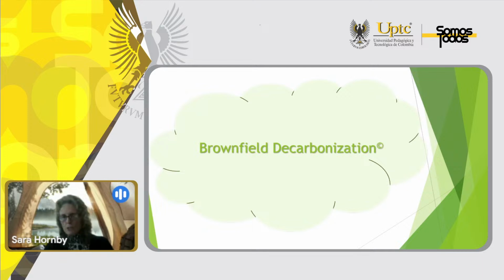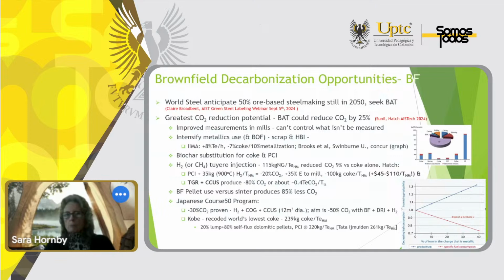So we look at potential brownfield decarbonization. Blast furnaces, we anticipate still needing 50% of the blast furnace steel making until 2050. So we're looking at best available technology. So the greatest decarbonization potential comes from the blast furnace side, and best available technology has already been shown to reduce CO2 by 25%. But we can also improve that further by improving measurements in the mills, because you can't control what you can't measure. We can intensify the use of metallics in the blast furnace, and I'll show you the BOF as well. And that would be either scrap or HBI.